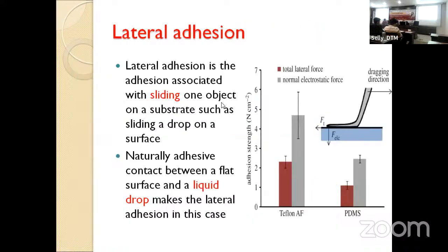What about lateral adhesion? Lateral adhesion is the adhesion associated with sliding one object on the substrate, such as sliding a drop on a surface. It's naturally the adhesive contact between the flat surface and the liquid drop that makes the lateral adhesion in that case. Look at that, the total lateral force using a Teflon surface, as total lateral force and normal electrostatic force. So we take into consideration the calculation of adhesive strength. You take into consideration the lateral adhesion effect. It's important for covering some materials like Teflon.